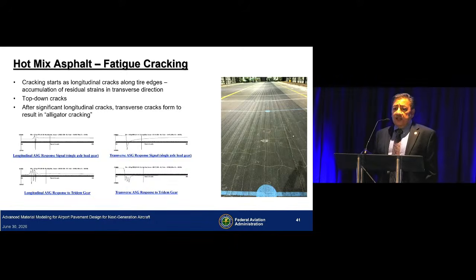Cracking, fatigue cracking. Now, one of the advantages of full-scale testing, accelerated pavement testing, is you can see the evolution of distress in these pavement structures. And when you look at cracking, I related it to the asphalt strains. So we have transverse strain gauges and longitudinal strain gauges, and the two show very different behavior. What you see on the left side is a strain measurement from a longitudinal strain gauge, single axle, 3 axles, so you see 3 peaks and single peak.